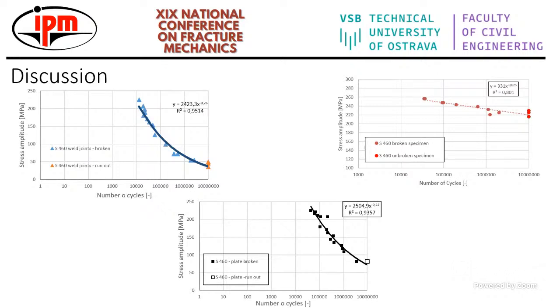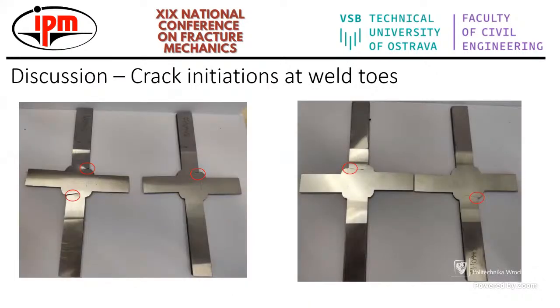Yeah, because I suppose that it is initiated from the same defect, and also I suppose for the plate it is quite understandable that the crack initiated at the surface, where is the corner, where the stress is at a higher level than in the middle, where there is no typical stress concentrator. Okay, then we looked at how the crack initiation happened, and we found that it is all as we supposed and know from the literature: it comes from the weld toe. You can see in the red rings like this that it is always over the weld part.